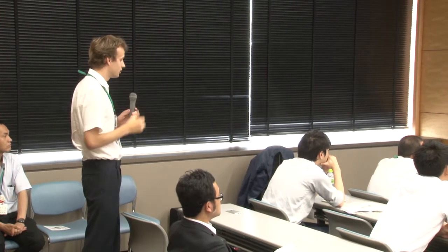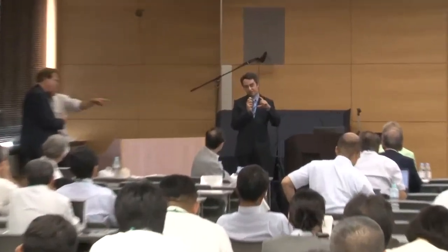Okay, so we have the porous silicon layer, and we reorganize it during a very short high temperature bake, which we actually do inside the epitaxial reactor. So we ramp up the temperature to the deposition temperature, which is typically 1100 degrees, and then we stay for a few minutes. What we did is we looked at the evolution of the reorganization as a function of time. And actually the reorganization is already finished after around 2 minutes, so we only do 2 minutes.